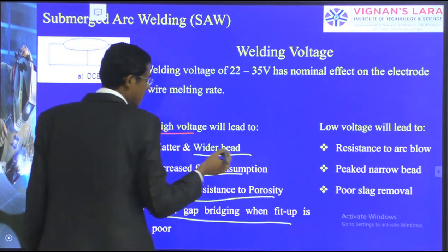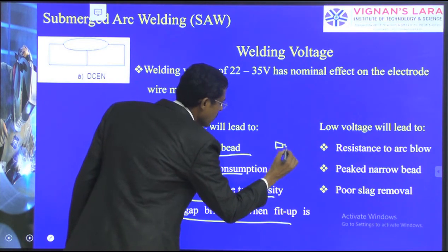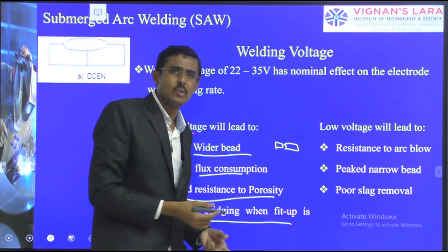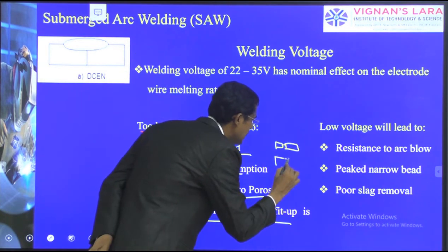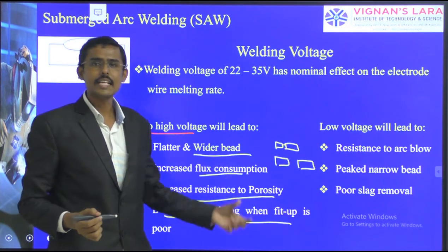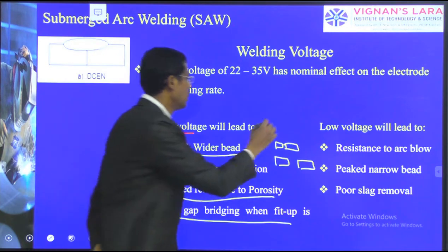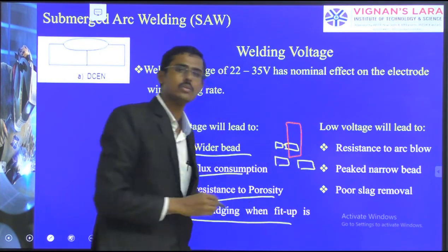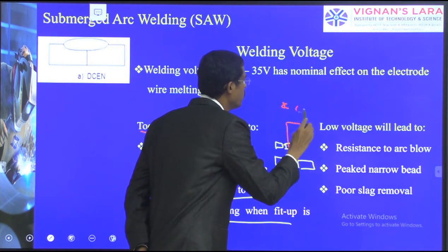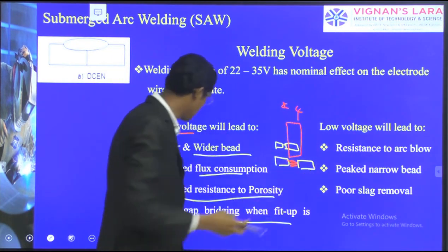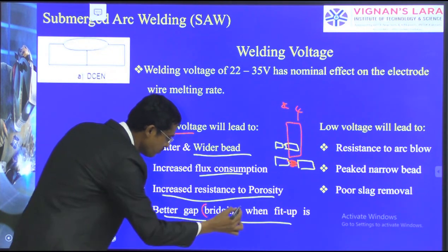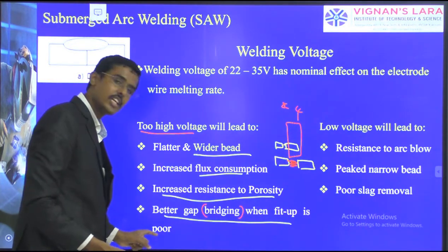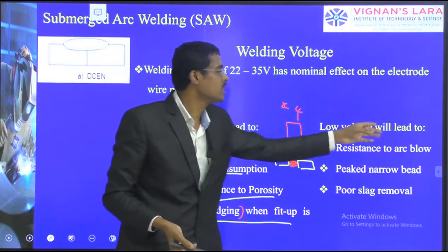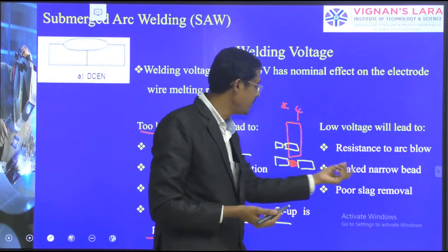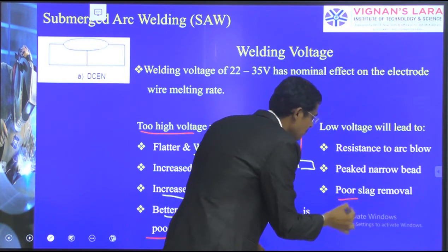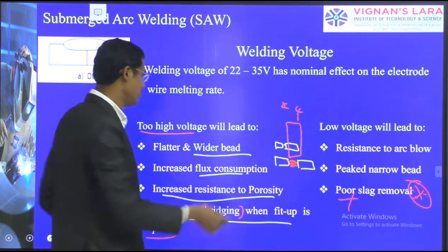Let us consider I have to fit two components in such a way, but the fit-up is not good. The welder or fitter has not done it properly and has fitted with a wide gap. At this time I can use a large diameter electrode, instead of 2 mm diameter I can use 4 mm diameter, and then I can fill this gap. Some better gap bridging. The terminology is gap bridging; when the fit-up is very poor, at some time it will be helpful. So low voltage will lead to resistance to arc blow. Similarly, peaked narrow beads and poor slag removal, these all are not good. They should be modified.